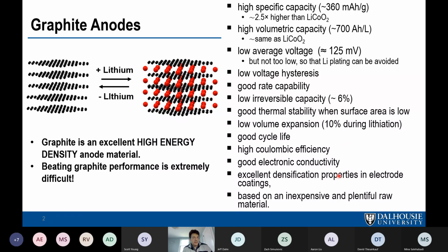You can densify it. In fact, in some cases, you might add graphite to the cathode as a lubricant, a calendering lubricant, to improve density. And it's highly abundant, and you could just take it from the ground directly. So with characteristics like that, it's very difficult to improve upon. And we'll see if we can improve on it a little with alloy materials. I think the best theoretical improvement you can possibly make is something like 20% increase in energy density in the cell, but that's theoretical. And we'll see the reality might be a bit lower than that.